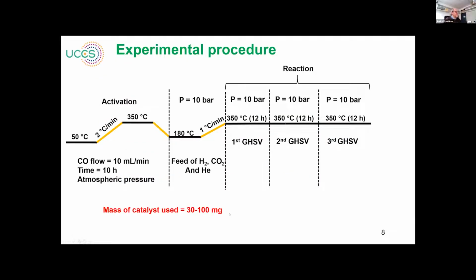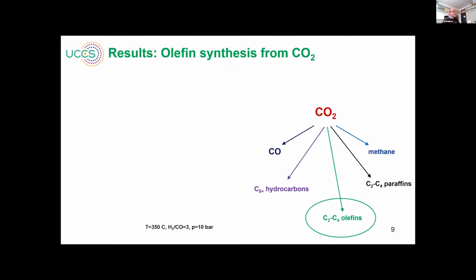So here's the experimental procedure which was used. We have activation, which is all the time the same for all catalysts and all tests, because we conducted 2 high throughput tests. The activation is in CO, because it was optimized during our previous work. And we also have tests at 10 bars with different gas phase velocity. By changing gas phase velocity, we change contact time and the conversion, and we can see variation of selectivity as a function of conversion.